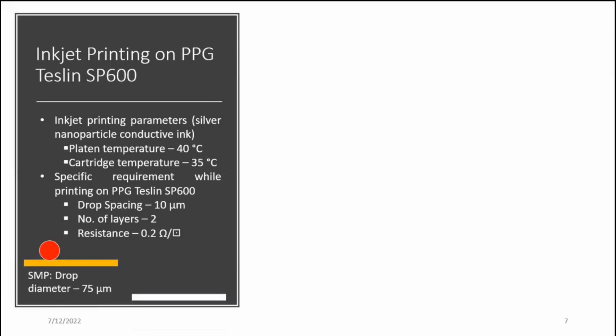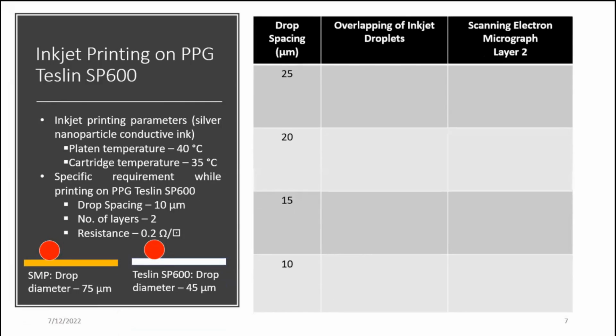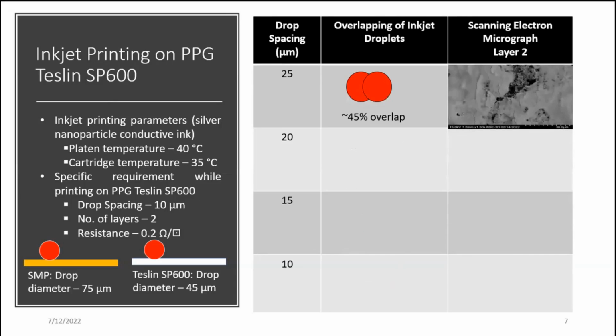So it was pretty big, but when we convert it to Teslin SP600, the drop diameter is only 45 micrometer. And we try to figure out the conductivity in terms of different drop spacing, such as for 25 micron, when we observe only 45% overlap, we took the same images and we can clearly see some breakage in there. There is no conductivity at all.